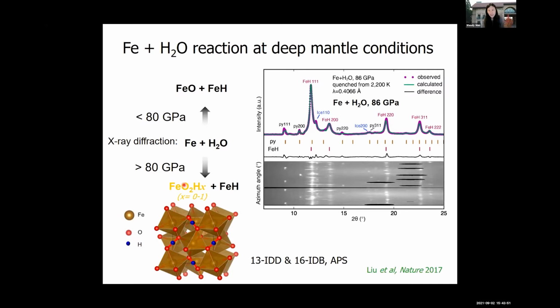And then he found an oxygen-rich phase of hydrogen-bearing iron oxide, FeO2Hx, because there can be variable hydrogen from 0 to 1, along with some iron hydride. So you can see in the diffraction pattern on the right these products. This new hydrogen-bearing iron oxide has very similar structure to pyrite. And if you think about the periodic table, oxygen sits right above sulfur. So the structure is basically the same as FeS2, but with oxygen replacing sulfur in the lattice.